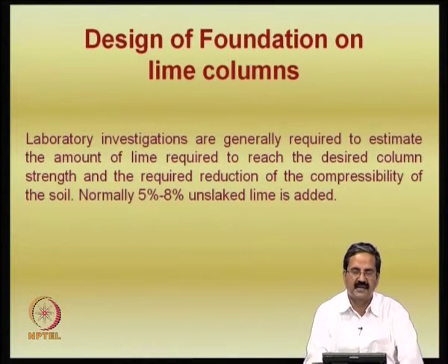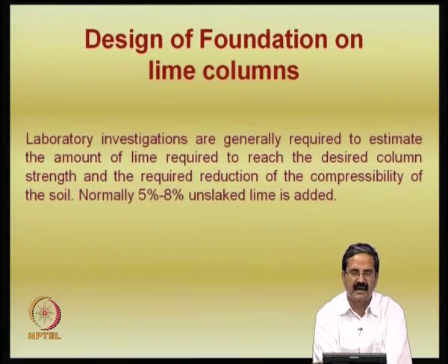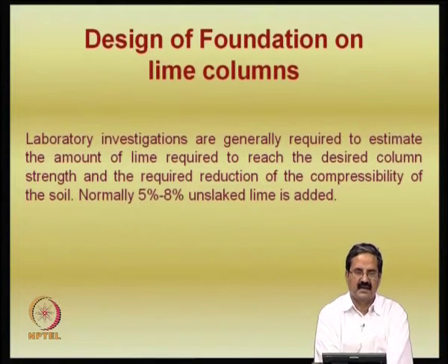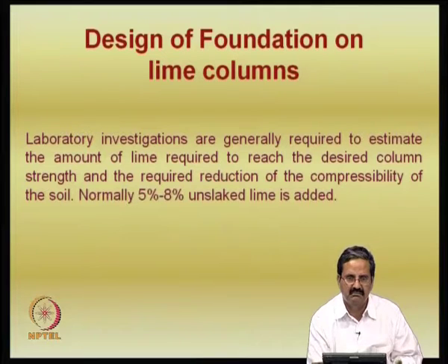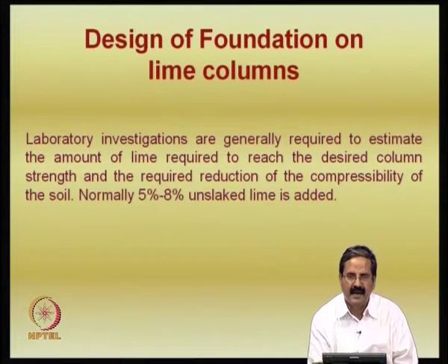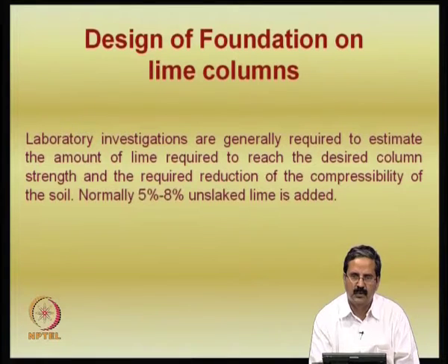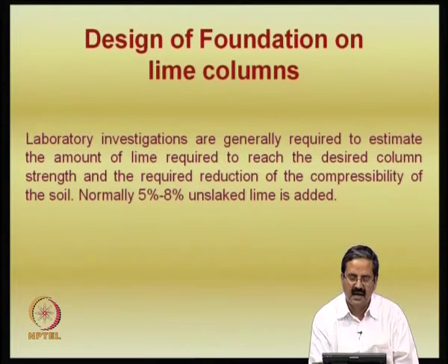What we should do, as I just mentioned, is take the unconfined compression test as the basis. For example, you are trying to construct an embankment on a soft soil: take the soil at its natural water content, make a sample, add lime, make a sample and get its unconfined compression test or all other properties. You need to estimate strength, compressibility, permeability, everything. Measure all the properties in the undisturbed state, and then measure them at various lime contents like 2%, 4%, 8% or whatever.